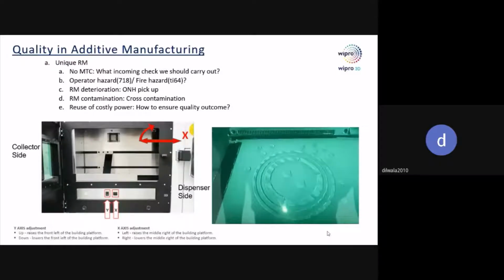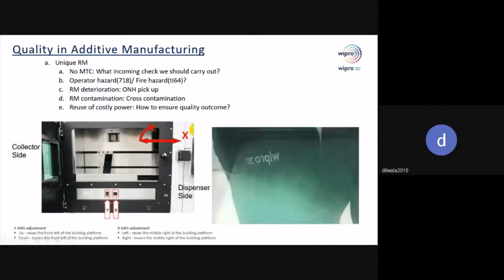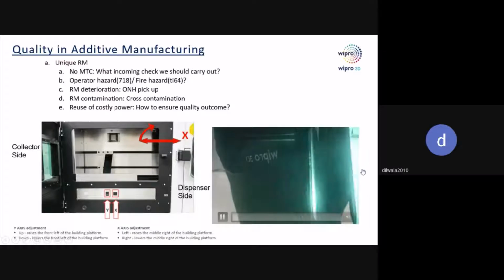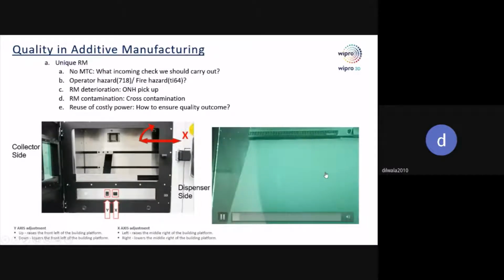So once one layer is built, our build platform goes down by a predefined layer thickness. After it goes down by the predefined layer thickness, the recoater goes towards the dispenser side, collects the powder and spreads it onto the bed. So it collects the powder and spreads it onto the bed. Now again laser sintering starts.